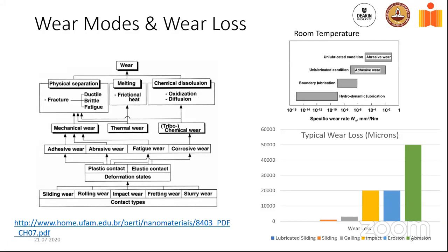Right. So the point I really wanted to make was that you can essentially have an order of 10 to the power of 16 difference in wear rate, depending on what mode you are operating. So the wonderful zone that you would like to be in is hydrodynamic lubrication. That's a Toyota car, where you can essentially start the car, run it for 400,000 miles, and you still find that it's good. And the folklore is that if you start taking a look at the amount of wear that is taking place in the cylinder piston ring, it's in the range of 15, 20, 25 microns. So the wear is so infinitesimally small when you have a lubrication working really well and working in tandem with the component surfaces.